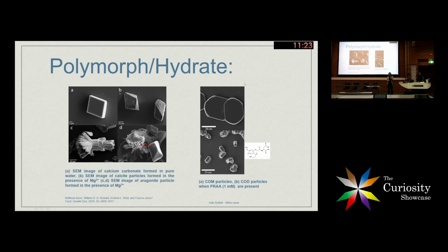And actually, this is one of the unsolved mysteries still in the area of crystallization. We know that as the oceans of the world have increased their magnesium content, we get more aragonite forming in shells and other sea organisms. But aragonite is less thermodynamically stable than calcite. So while we know that magnesium is involved in the formation of aragonite, why does the aragonite not dissolve away and form calcite over time? Still an open question.